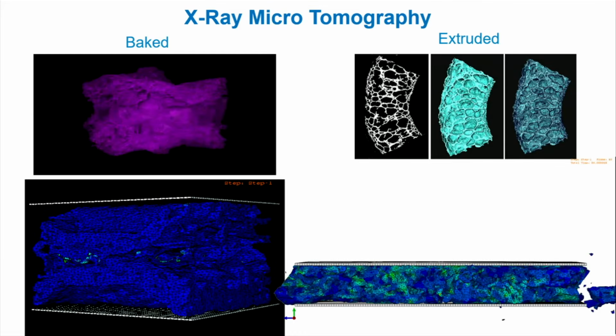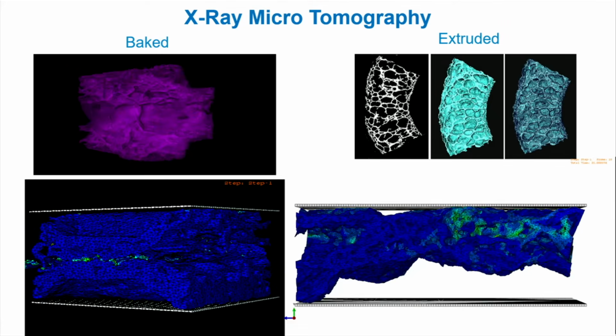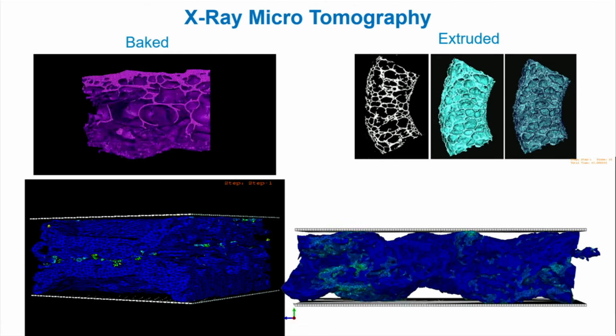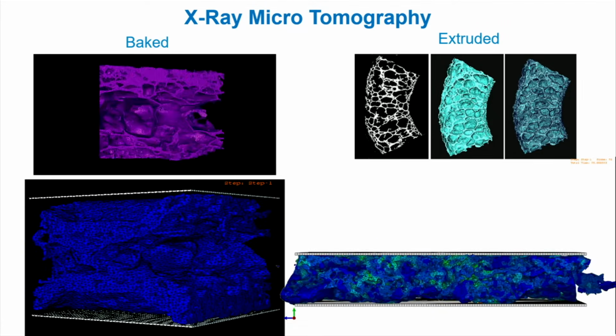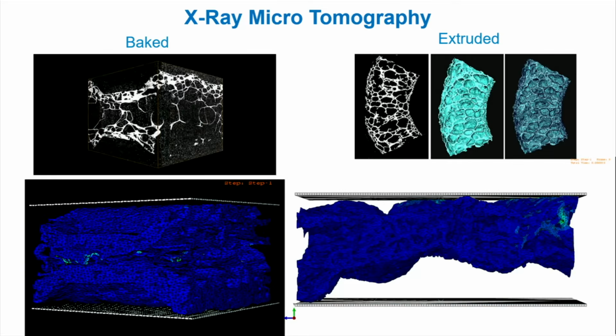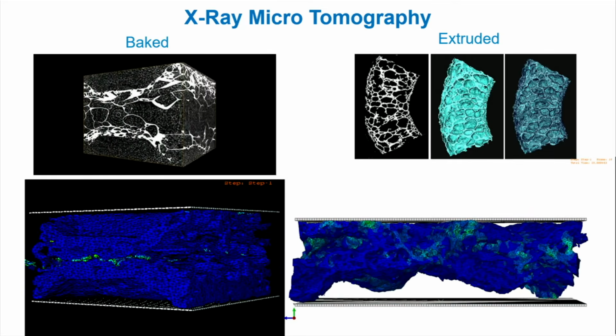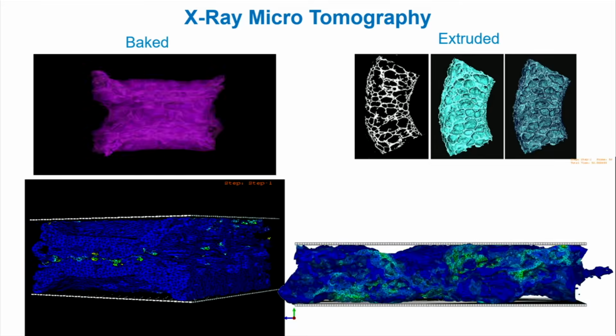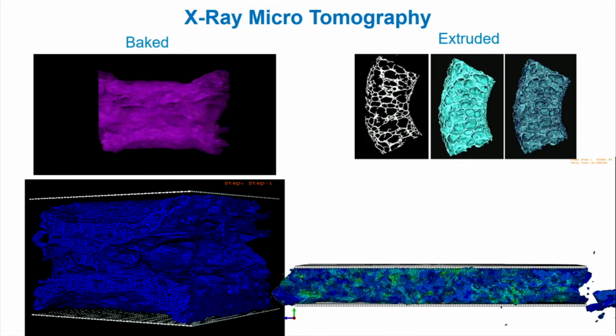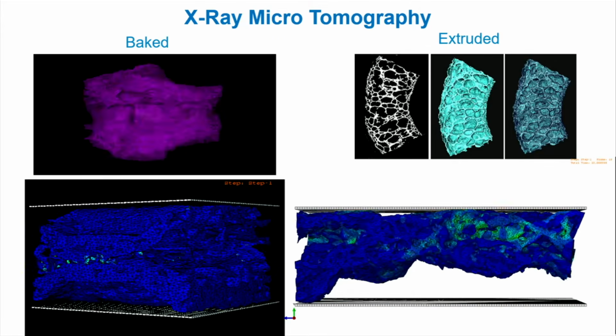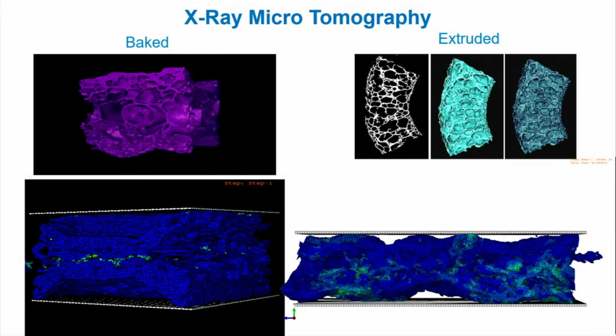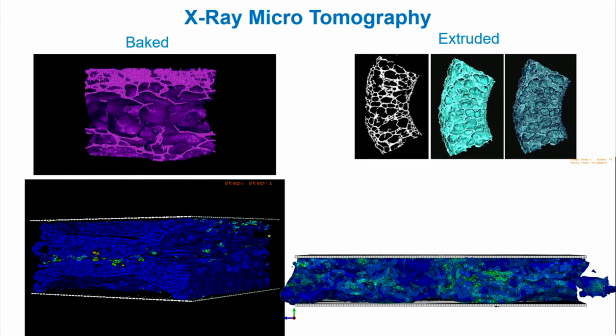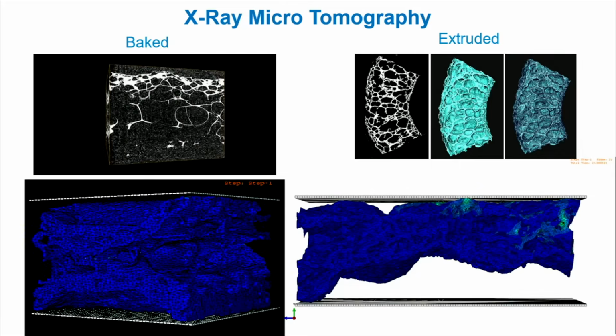And we found that indeed the extruded product has much stiffer cell walls. The other thing we could do, of course, once we have the two geometries, is to input the same material properties for the solid wall, and then you pick up the differences. Again, the extruded one came out stiffer, and this is just the effect of the microstructure. So extrusion seems to lead to stiffer microstructures because of the different material in the cell wall, as well as the different architecture of the cellular material.